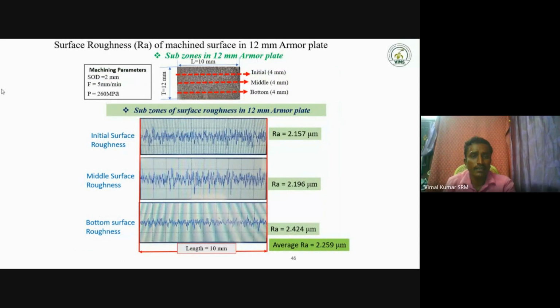Here this is the plot of surface roughness measured in the surface roughness machine. Generally, we measure the top, middle, and bottom surface roughness. Whenever the surface roughness tip travels along the cut surface, this kind of graph is plotted by the machine. From that measurement, finally we get 2.157 micrometer, 2.196 micrometer, 2.424 micrometer. These are the values finally concluded from the surface roughness tester. If we need the graph, we can take a printout from the machine.